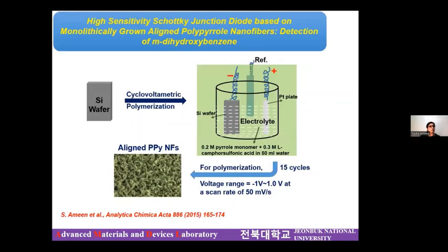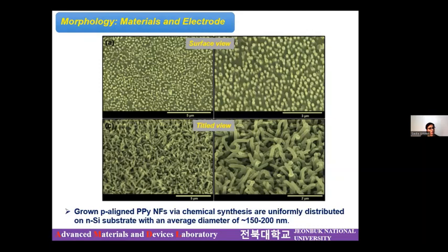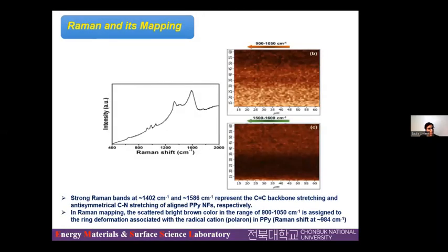After that, we have also tried to apply conducting polymers. Here, as we know, polypyrrole is a conducting polymer, and we have made aligned nanofibers of it, and applied it for the detection of meta-dihydroxybenzene. From the morphological images, if you see the surface view, it looks more like dots. However, when we take the tilted view, it clearly shows the appearance of nanofibers over the surface of the silicon. And this is again some of the characterization that we performed just to make sure of the structural, crystalline as well as the morphological properties of the synthesized materials.